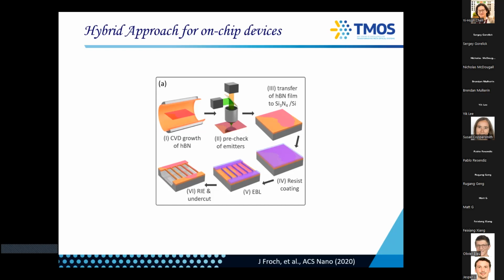The reason why we choose silicon nitride is because silicon nitride is very easy to fab. And when I mean easy, I mean that the recipes are well established. You go and you etch your photonic structures and the success rate is quite high. And the undercutting is relatively simple. And so you can then deposit your HBN and do EBL and pattern your devices with the HBN on top.